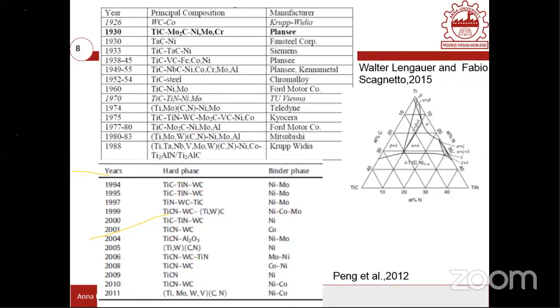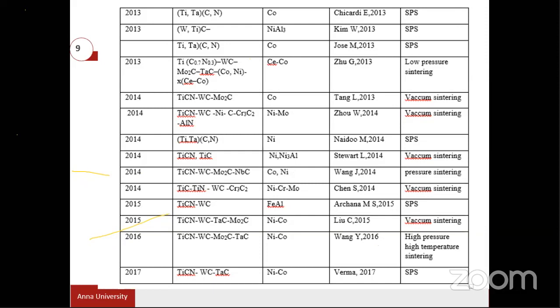And then later in 2011, people modified TiCN with molybdenum, tungsten, and vanadium, where in the presence of nickel and cobalt binder, it is recommended as one of the cutting tool materials. And there are several other compositions also proposed. You can modify with tungsten carbide, niobium carbide or tantalum carbide, and some other compositions also. So these are different compositions people recommended.